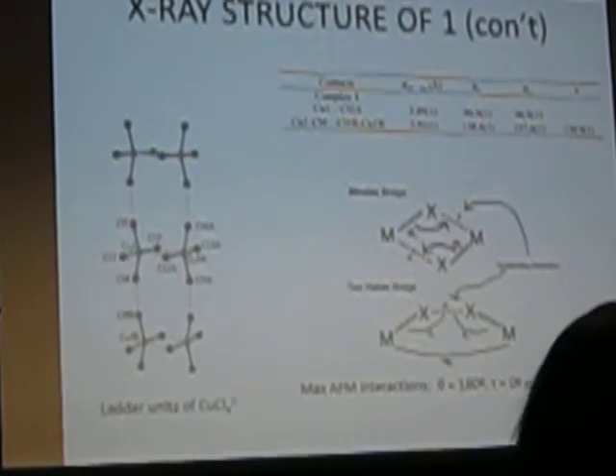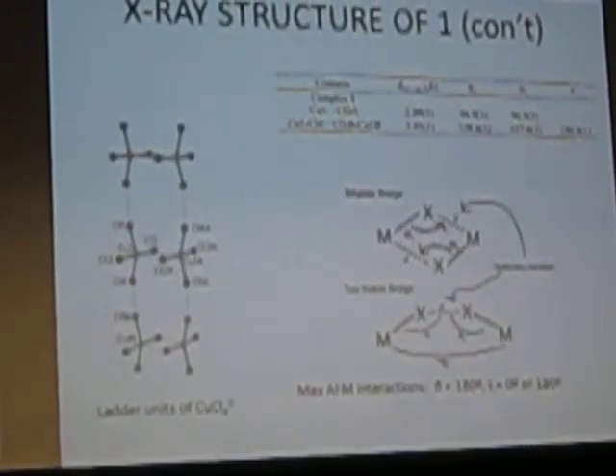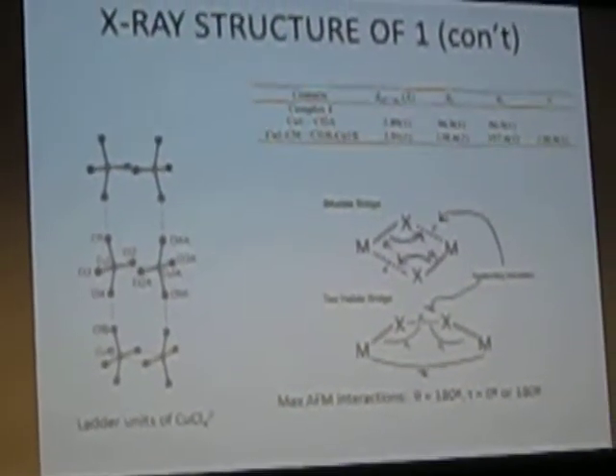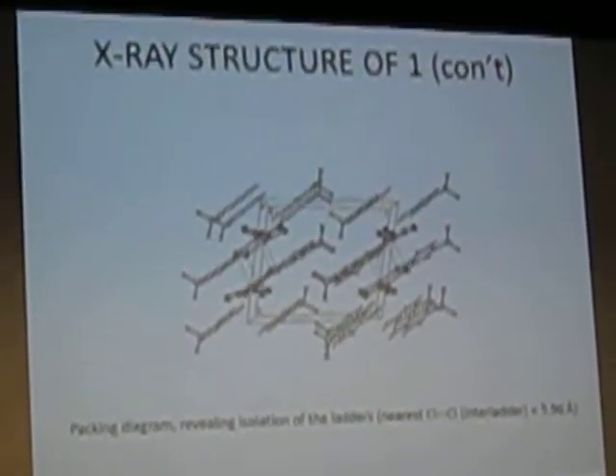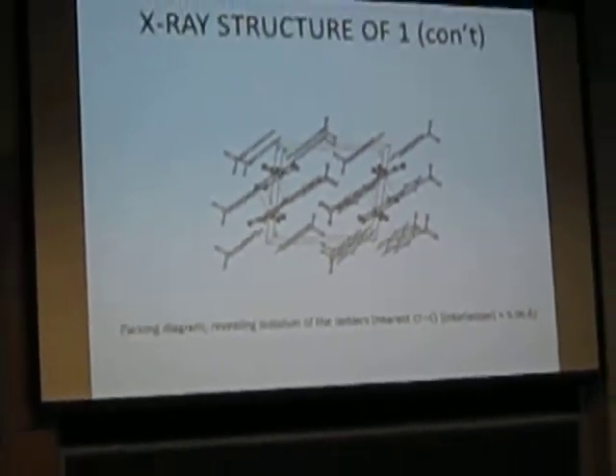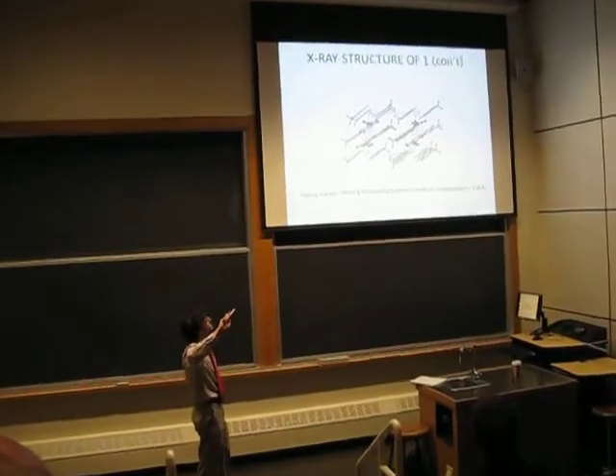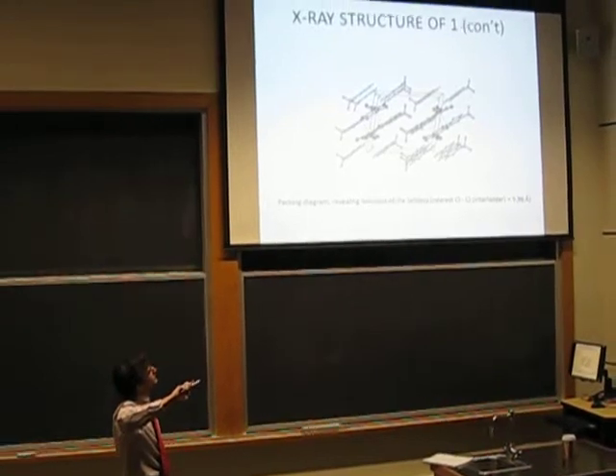So this is an example of a spin ladder, or at least we expected it to be a spin ladder. So what does the magnetism say about this material? Well, first of all, we want to take a quick look at the packing. This is just to show how isolated the ladders are from each other. You can see this zigzag chain of chlorine atoms separates the two ladders from each other, and the distance between the ladders is about 5.9 angstroms. So they're quite far apart, and we expect very little 3D interactions.